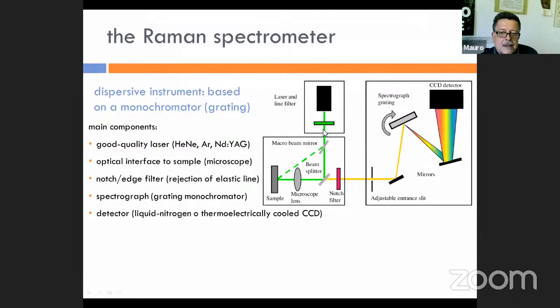And then we send the laser light onto the sample by an optical interface, and the same optical interface is used to collect the scattered Raman light. Since Raman is an incoherent scattering process, the Raman light is emitted over the entire solid angle. So we need good collection optics to collect most of the Raman signal.